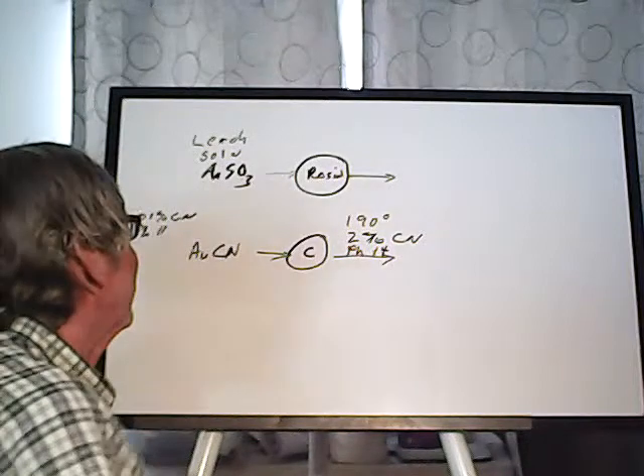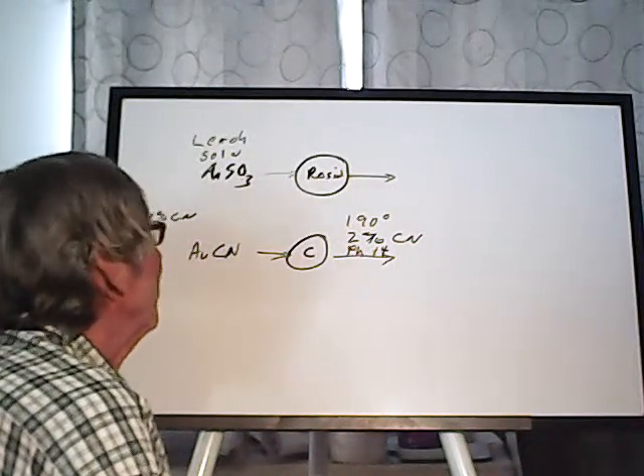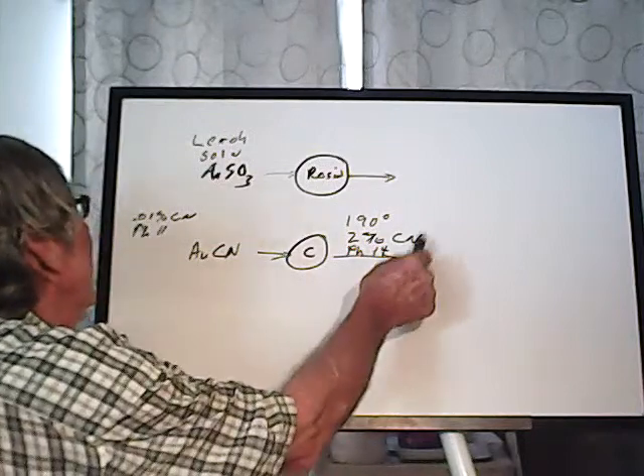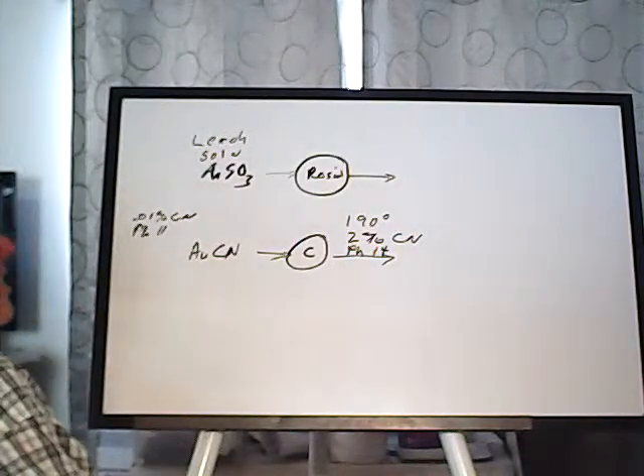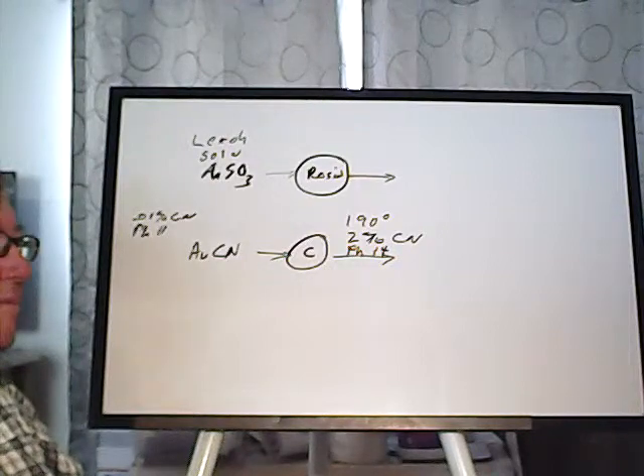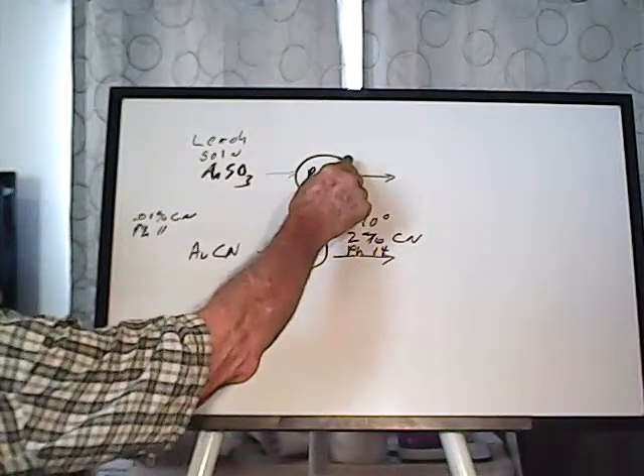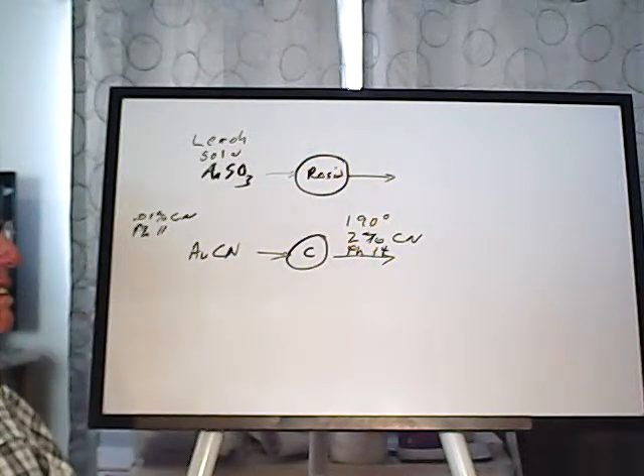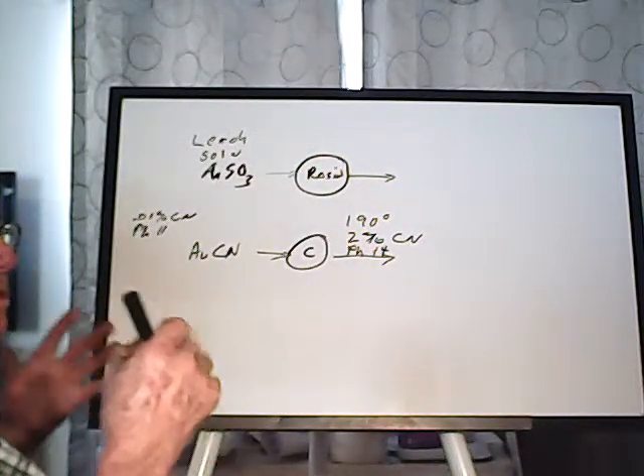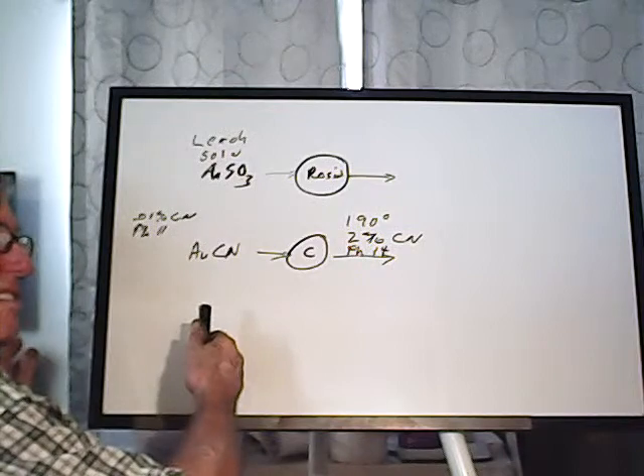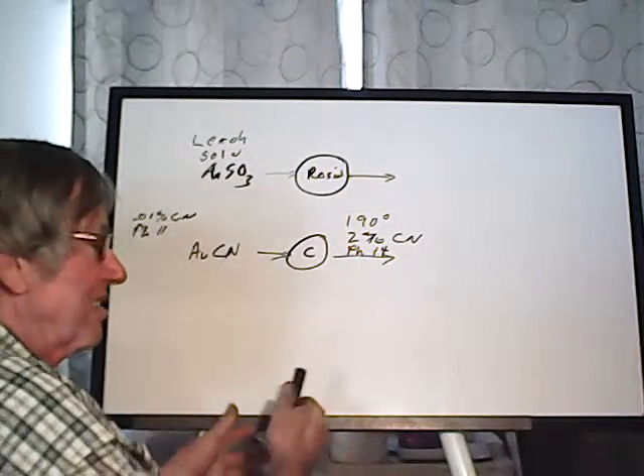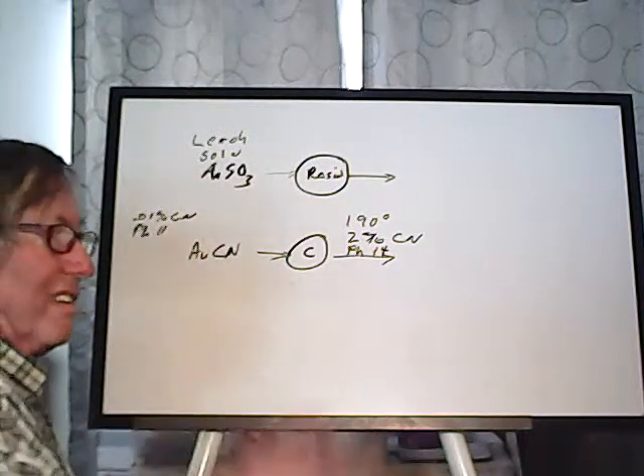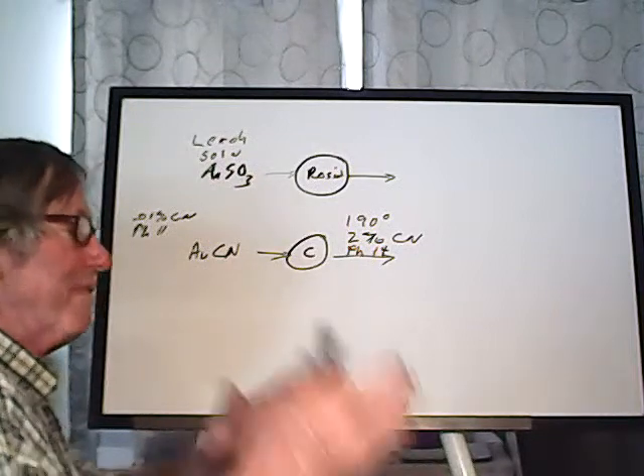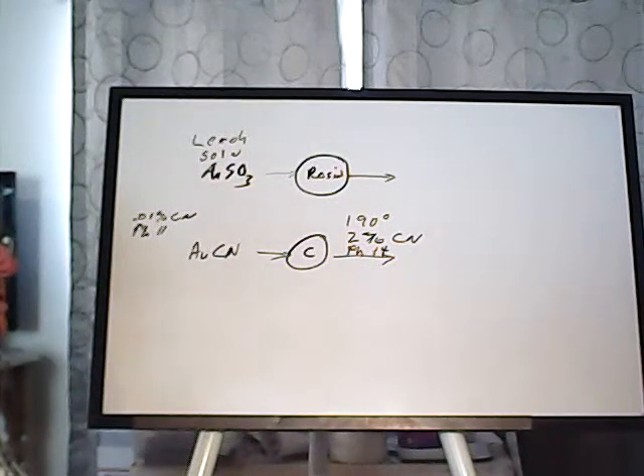That is some really, really dangerous stuff. The stuff that we should be doing here should be not nearly so extreme. But what exactly we're going to do to this resin has yet to be determined. But that's why we're doing it and how it works. Under the leach solution conditions, the gold goes into the resin. Then you separate the resin from those conditions, put it into other conditions, dissolve the gold back off of the resin, and then electroplate it or precipitate it.